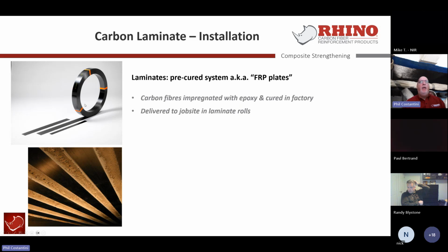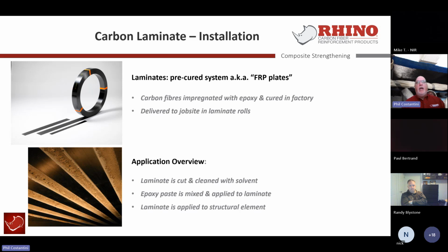So just so we know, the higher strength goes to the laminates, and they're used often in very pristine applications of undersides of slabs when you have long longitudinal reinforcing or long spans that are required. And these coils are usually about anywhere from 50 to 100 meters in length and can be delivered to the job site in that form that you see above there. The important thing is that it's cut and cleaned with solvent. The epoxy paste is mixed and applied to the laminate, and then the laminate is applied to the structural element that the reinforcing is being applied to.